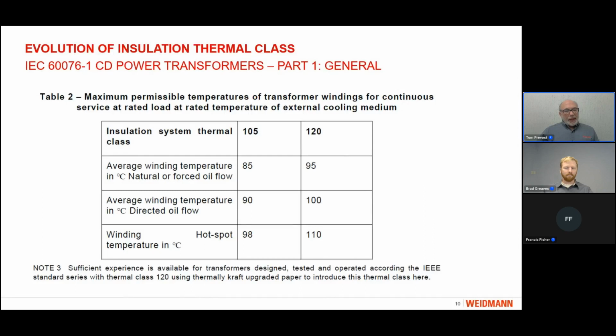I mentioned that the IEC transformer standard is being revised. That draft was circulated the first time about 6 months ago. In fact, there were more than 1,000 comments on it, so it will take some time to be circulated and the comments addressed. In this new revision, we can see that in Table 2, there are now 2 thermal classes: the traditional 98 degrees hotspot, and then if you use thermally upgraded paper, a new thermal class of 120 with a hotspot temperature of 110.